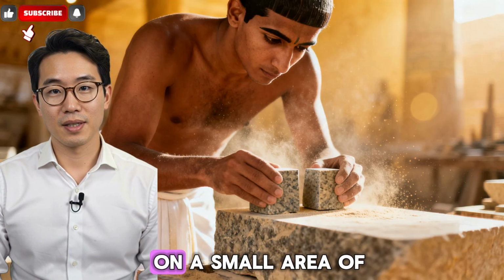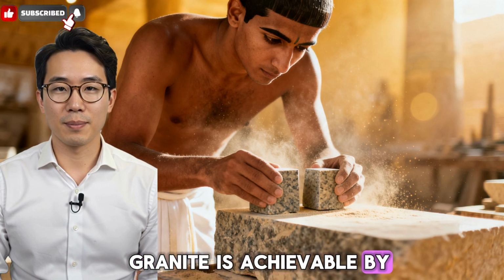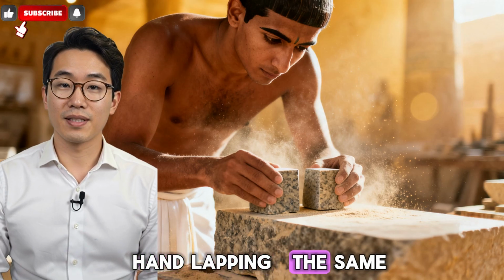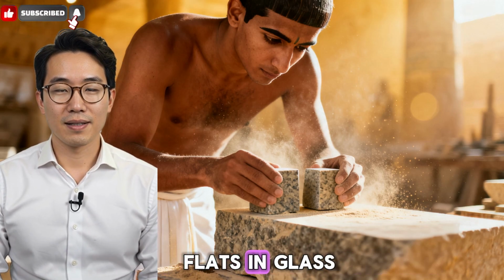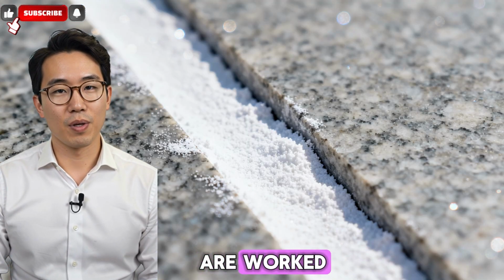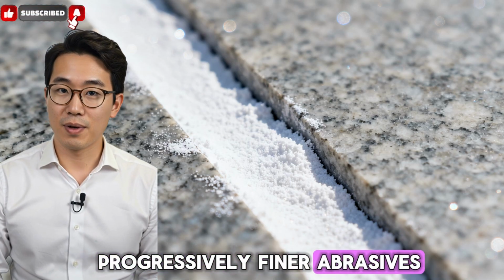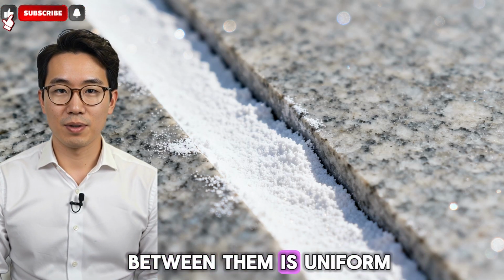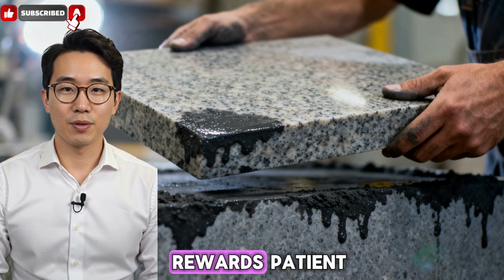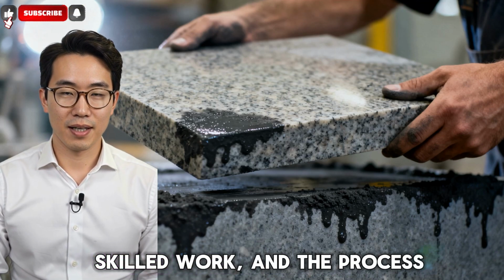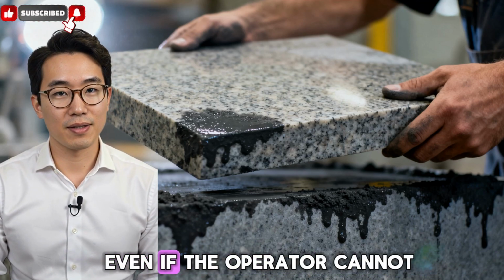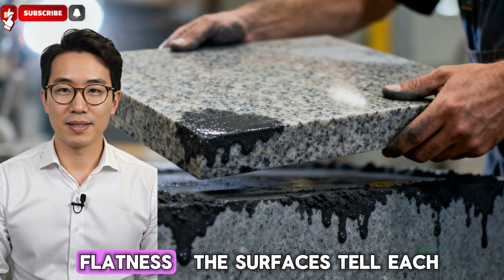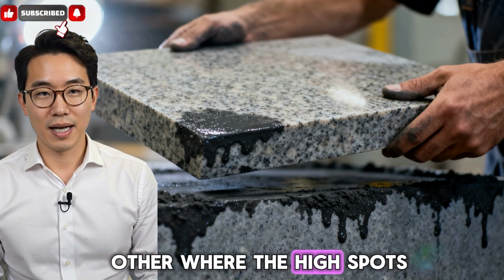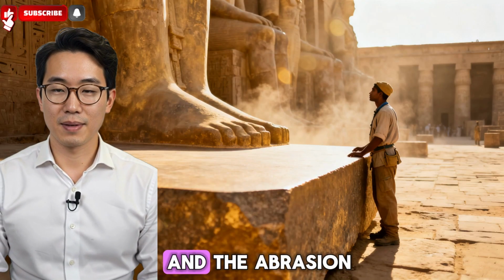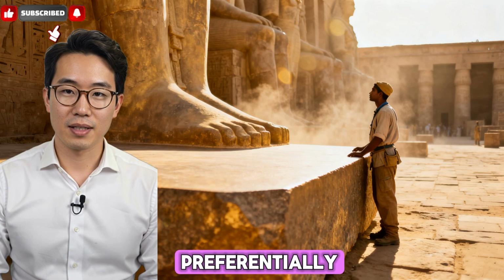Producing a flat surface on a small area of granite is achievable by progressive hand lapping, the same process used to produce optical flats in glass, in which two surfaces are worked against each other with progressively finer abrasives until the contact between them is uniform. The physics of hand lapping rewards patient, skilled work, and the process converges on flat even if the operator cannot directly measure the flatness. The surfaces tell each other where the high spots are by the uneven contact, and the abrasion removes the high spots preferentially.